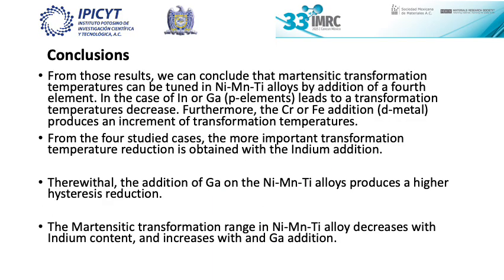So the conclusions: from those results, we can conclude that the martensitic transformation temperatures can be tuned in nickel manganese titanium alloy by the addition of a fourth element. In the case of indium or gallium, that leads to a transformation temperature decrease. Furthermore, chromium and iron addition produce an increment of transformation temperatures. For the four studied cases, the most important transformation temperature reduction is obtained with the indium addition.